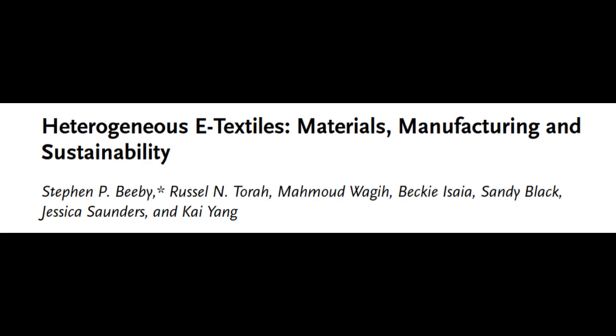And I saw a note in there about coils for wireless power. Yes, that was a neat finding highlighted in the source. A study compared different ways to make coils for wirelessly transferring power. How'd they make them? They tried standard embroidery with conductive thread, they tried printing with conductive ink, and they tried a technique called couching. Couching? Yeah, it's an embroidery technique where you basically stitch down another, often thicker, thread onto the fabric surface. In this case, they couched down a special multi-strand conductive wire called Litz wire. Litz wire, okay. And what did they find?